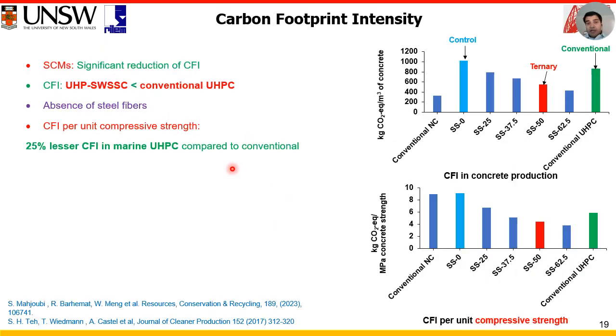Now we come to the carbon footprint intensity and saw that utilizing supplementary cementitious materials can significantly reduce the carbon footprint. The carbon footprint intensity in the marine UHPC can be as much as 25% lesser than the conventional UHPC, mainly because of the absence of the steel fibers. We do not have any steel fibers in our mix to avoid the corrosion chances.